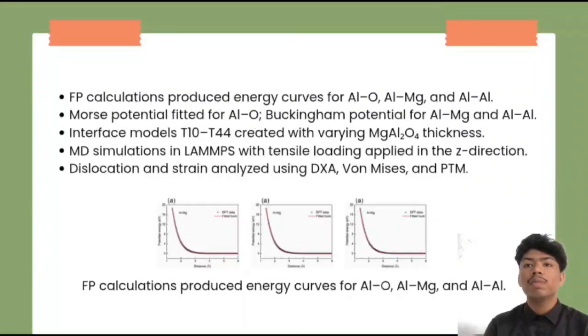The Morse potential was applied to the aluminum-oxygen interactions due to its strong and partially ionic nature, while the Buckingham potential was used for aluminum-magnesium and aluminum-aluminum interactions, which are more metallic and repulsive, with the fitted potential parameters. The research team constructed 5 different interface models, each with a different thickness of the aluminum-magnesium aluminate layer: 10 angstrom, 20 angstrom, 28 angstrom, 36 angstrom, and 44 angstrom, referred to as T10 to T44.